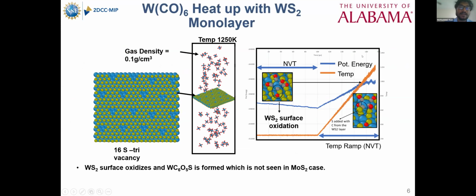From there, we did our second case study where we had the same tungsten hexacarbonyl heat up, but this time with the presence of a monolayer. Now, we added some sulfur vacancies in this monolayer. This monolayer is actually a tungsten disulfide monolayer with some sulfur vacancies. The reason we had sulfur vacancies is that it would increase the reaction rate, as well as the sulfur vacancies are the most stable vacancies in tungsten disulfide.